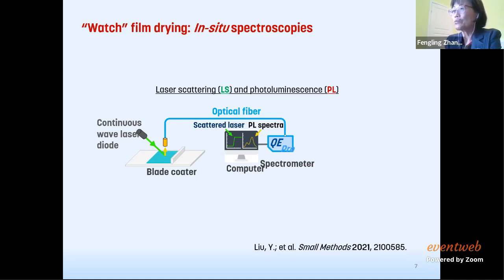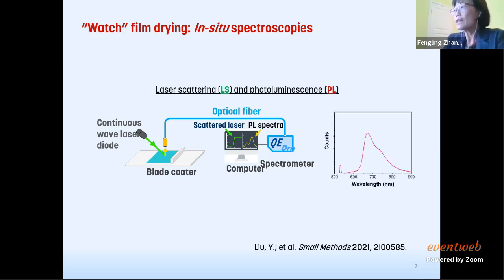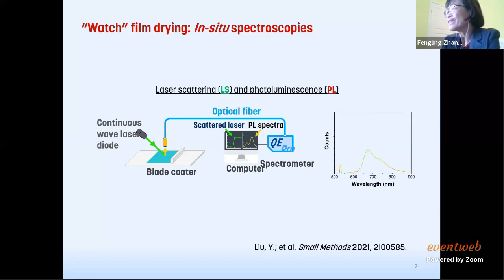So you see, we have the laser illuminating the surface during the solution drying when we do the blade coating, and then we alternately collect the signal from the laser scattering and the PL from the active layer. With that, we get a spectrum that looks like this. The broad peak is PL and the narrow one is laser scattering. It varies during the drying. You see the PL quenches and the laser scattering increases, because the material forms aggregates and the scattering gets stronger. So with this spectroscopy, we can in a way watch the film drying.